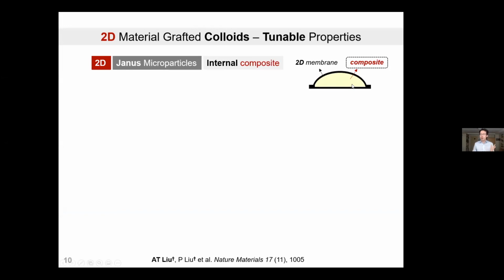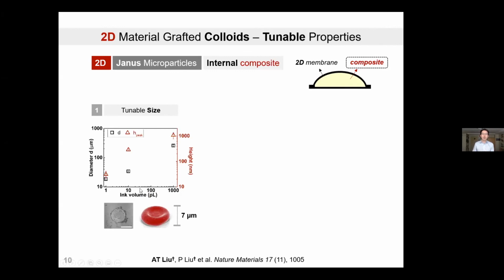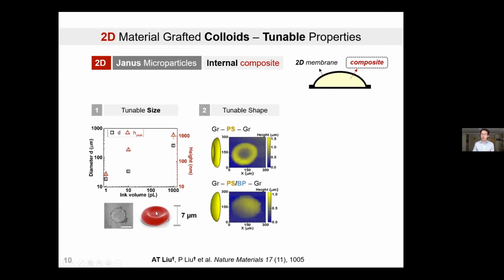But of course, by using different inks that we print using our inkjet printer, we can control whatever composite we're making inside this dumpling. By controlling the ink volume, we can tune the size of our colloidal electronic devices down to roughly the size of a human red blood cell. We can also control the shape and morphology of this little thing that we print by using different inks with different viscosity and surface tension. You can actually make them look like a human red blood cell with this colloidal shape.